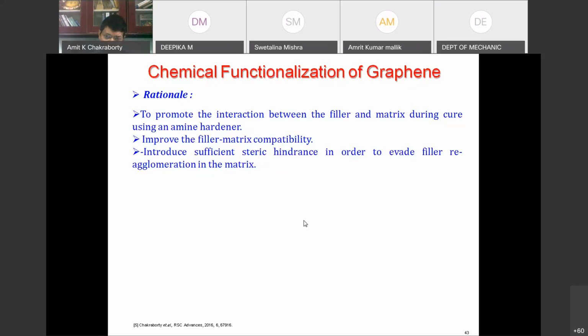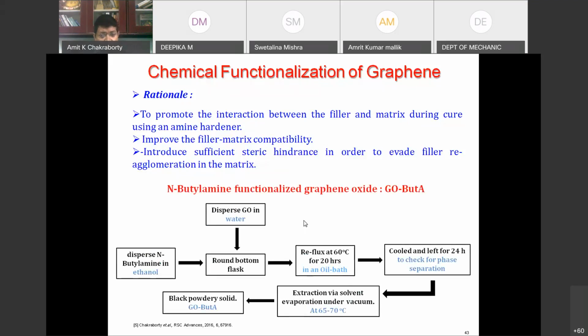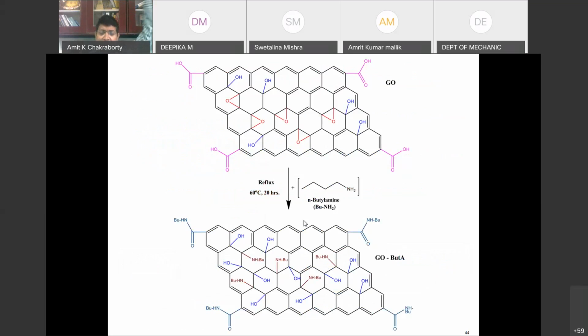So it will be making a very good bond with the resin. With this motive in mind, we have developed a butyl amine functionalized graphene oxide. These are the few steps that show how the graphene oxide was prepared, and from graphene oxide we prepared the amine functionalized graphene oxide, which has amine groups attached on the surface of the graphene. Schematically, it is like this.